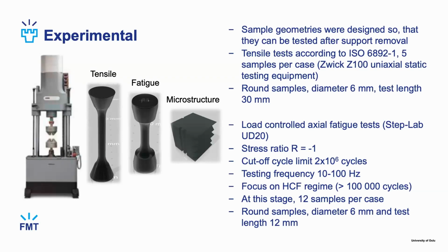For the fatigue, we used load-controlled axial testing with a stress ratio of R = -1 and with a cutoff cycle limit of 2 million cycles. And this is partly due to the high amount of samples we did in the project.